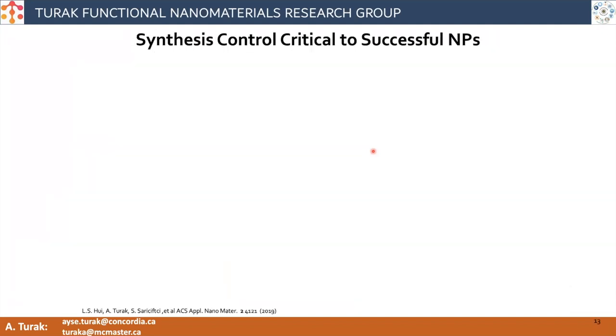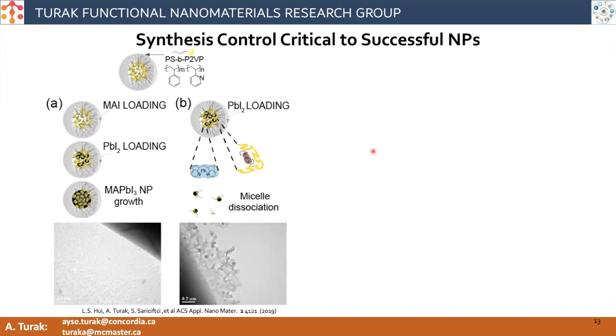So synthesis, and understanding the synthesis process, is really critical to having useful functional nanoparticles. And so we spend a lot of time trying to understand how particles are formed, but not only how they're formed, but how we can then use them, how we can bring out some interesting applications or functions due to that synthesis process. It's really critical to have good control over the synthesis because, for example, if you're going to make a perovskite material, in that case we use a two-step loading, where you load one reagent followed by a second one. And if you pick the right order of your two reagents, you get a beautiful array of nanoparticles at the bottom.